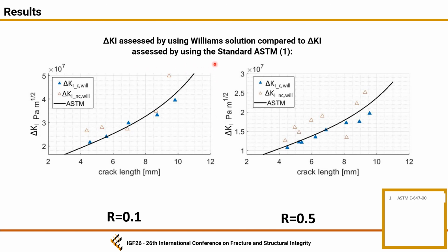The same results can be obtained for each stress ratio, where we can see that the stress intensity factors evaluated with the new formulation are in great agreement with the stress intensity factor provided by the standard. In this case, the data from the non-corrected theory, where the mean stress effect was not accounted for, are very scattered with respect to those obtained by using Williams.